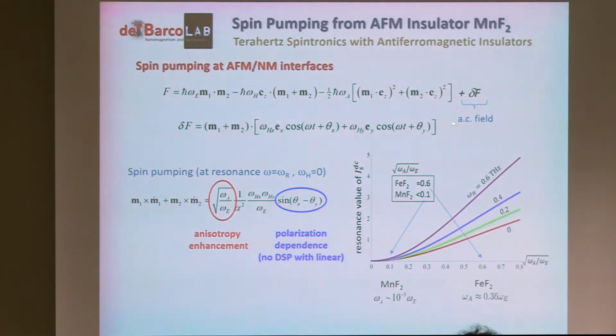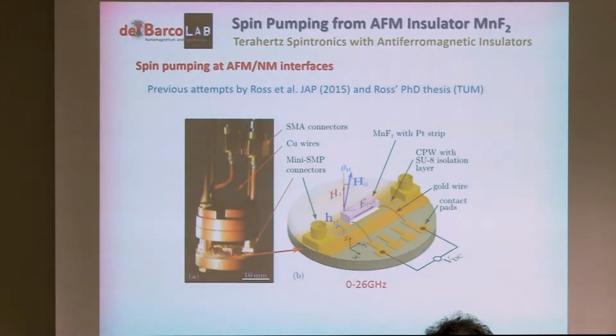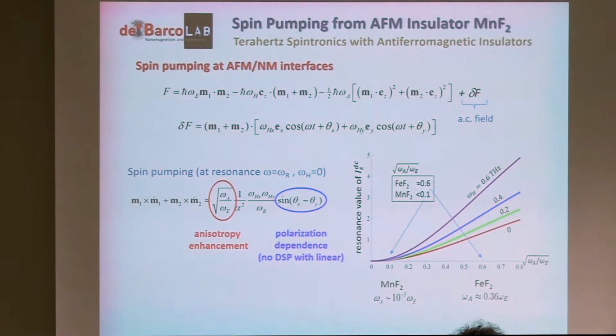So now we have the free energy that we were talking about before, but now we send microwaves. Well, we actually send terahertz radiation, or sub-terahertz radiation. This is a time-dependent perturbation to the Hamiltonian. And when you look at the spin pumping, that is basically the amount of spin current that will be expelled out of the antiferromagnet into the adjacent metal, it is going to depend on this factor, where you will see that there is an anisotropy enhancement of the spin pumping that you don't actually get in a ferromagnet.